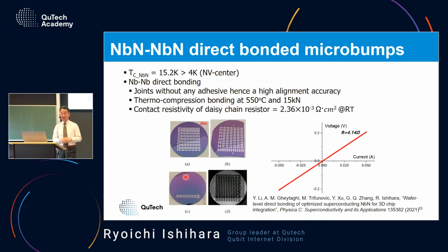We have reported that we can bond between niobium nitride and niobium nitride without an adhesive layer. And we measured the critical temperature of niobium nitride to be 15K, which is well above the NV center operation temperature. So this is suitable for NV center application. And we can make small microbumps because we don't need an adhesive layer between them. We bonded them by high temperature at some pressure,